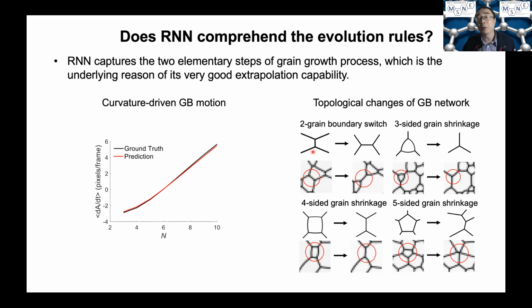And the second type of elementary step that happens during grain growth is the topological change that happens to the grain boundary network when small grains shrink and disappear, or when two grains switch edges with each other. Right. So for a two-dimensional system, there are 4 types of topological events. So this could be the disappearance of 3-sided, 4-sided, 5-sided grains, or 2 neighbor grains switching edges. Right? And in each one of the cases, we found the RNN model is able to correctly predict what will happen to the local topology of the grain boundary network after these events take place.